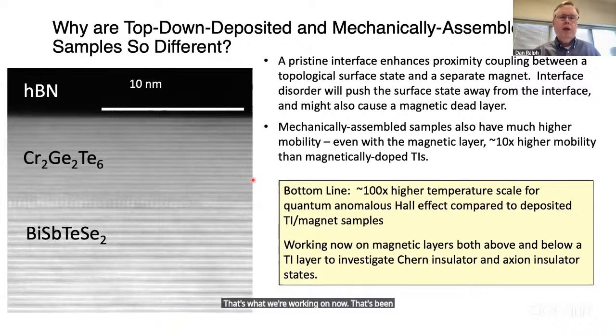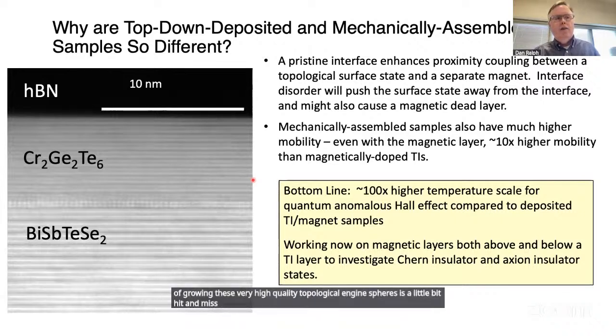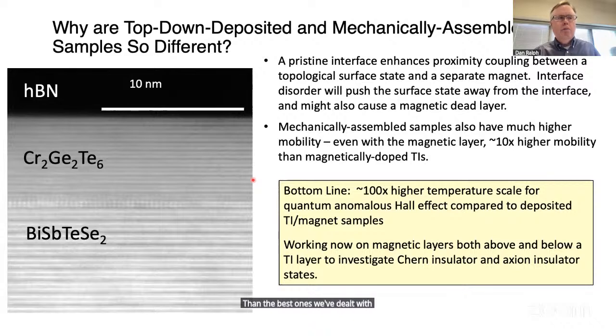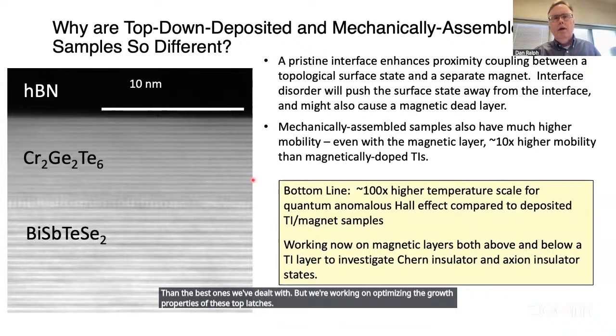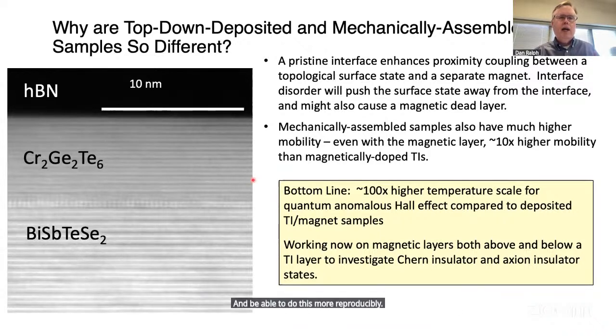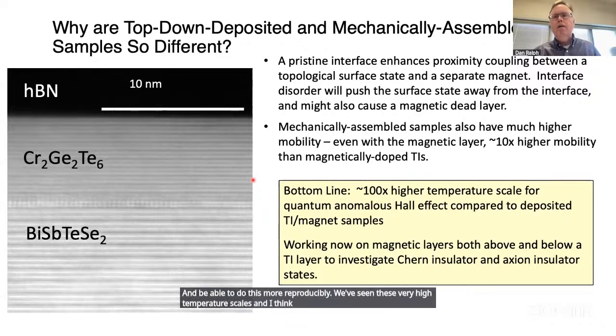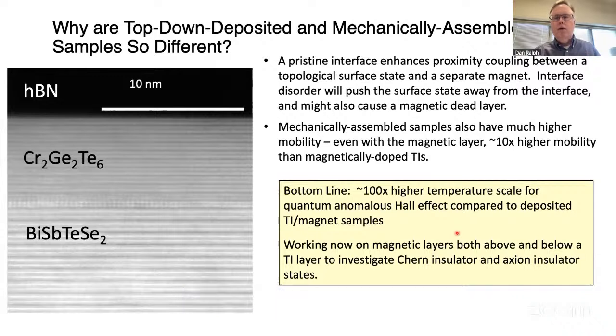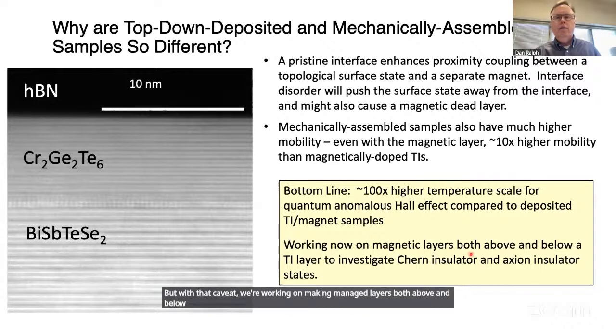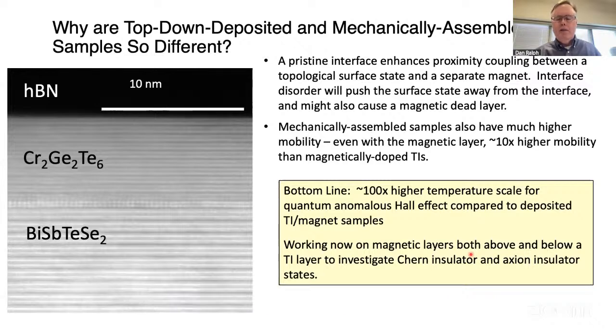That's been tricky mostly just because growing these very high quality topological layers is a little bit hit and miss. And so some of our most recent crystals have been lower quality than the best ones we've dealt with. But we're working on optimizing the growth properties of these topological layers and being able to do this more reproducibly. We've seen these very high temperature scales in three different devices so far. With that caveat, we're working on making magnet layers both above and below, and working to investigate both the Chern insulator state and the axion insulator state that come about once we have magnets on both sides.